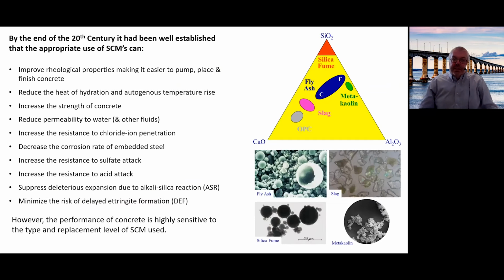So by the end of the 20th century, we pretty much demonstrated, with all the research that was conducted, that SCMs really were invaluable. It took a long while to convince people and regulatory authorities, but I think by the end of the 20th century, most people were convinced that fly ash, slag, silica fume and natural pozzolans, where they were still available, were good things for concrete, especially for concrete durability, and reducing permeability, increasing the resistance to chloride ion penetration, and also increasing resistance to things like sulfate attack, acid attack, ASR, and